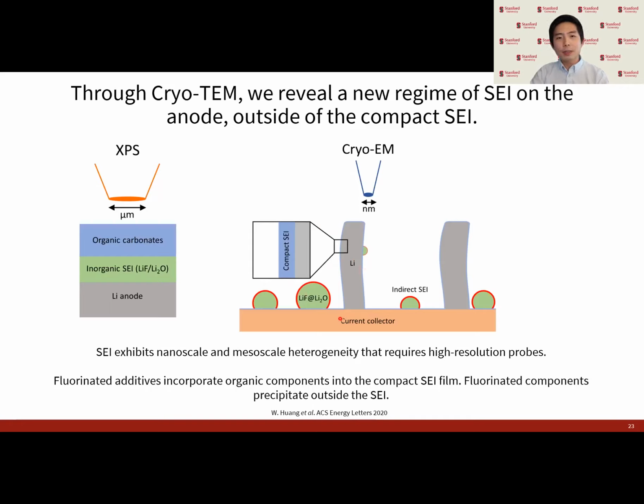We can see that there's this whole new regime of the SEI beyond this compact SEI film, where these inorganic lithium fluoride particles are sparsely decorating the electrode surface rather than incorporating into the SEI film. And finally, we can see that for this FEC additive in particular, it's the organic components that incorporate, while these inorganic fluorinated products precipitate outside. And that means they likely contribute less to the actual lithium cycling stability. And from a general design perspective, it then seems like the fluorination of these electrolyte additives likely aids in their reduction, but may not necessarily provide direct electrode protection.